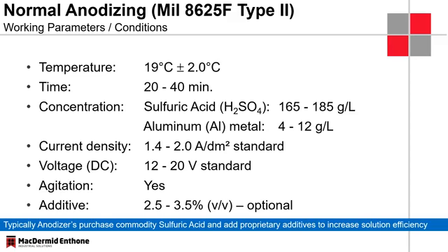When people talk about these additives that will increase efficiency, it will plate faster. It doesn't actually plate faster, but what it does, it dissolves less aluminum oxide from the surface, and therefore it appears that we have a higher thickness and a higher plating rate.